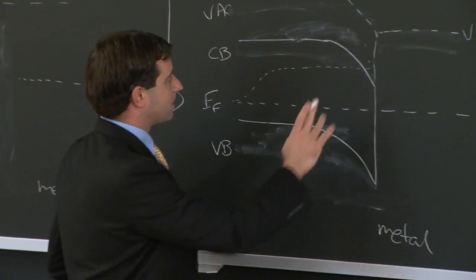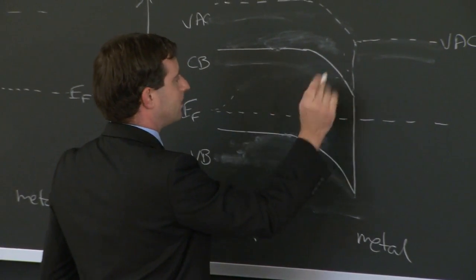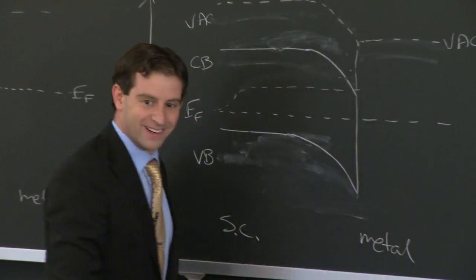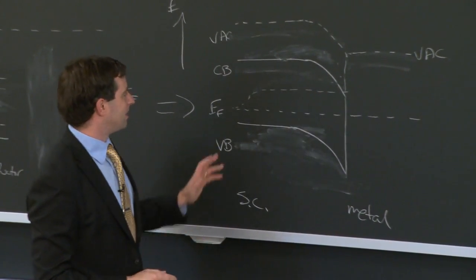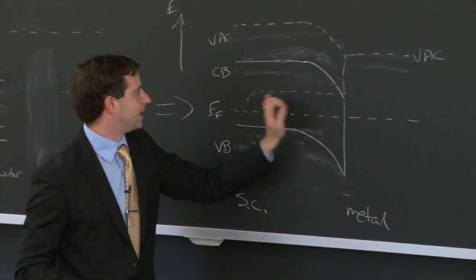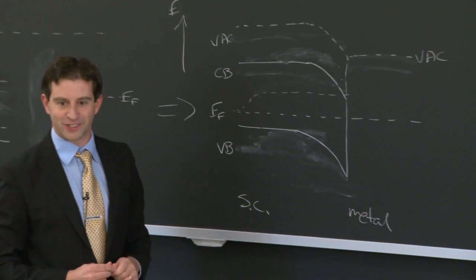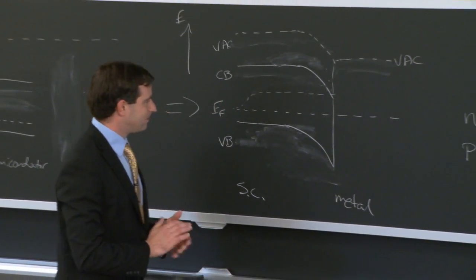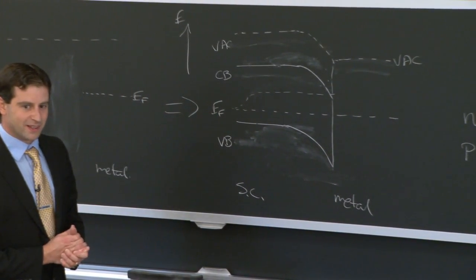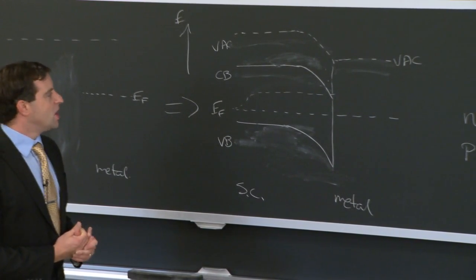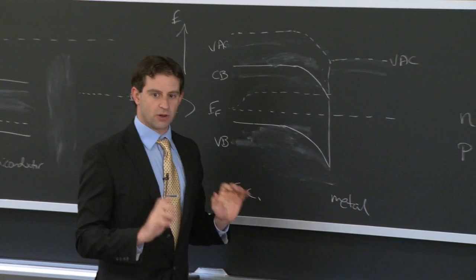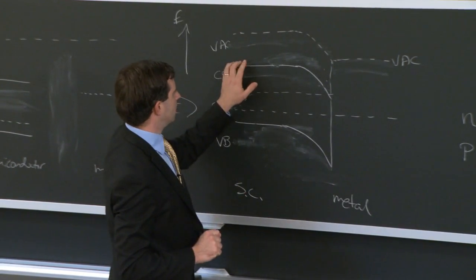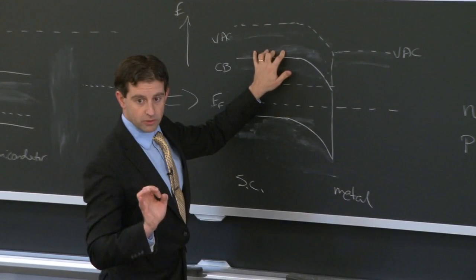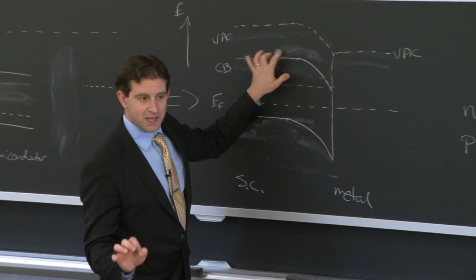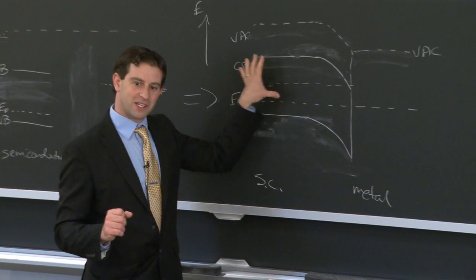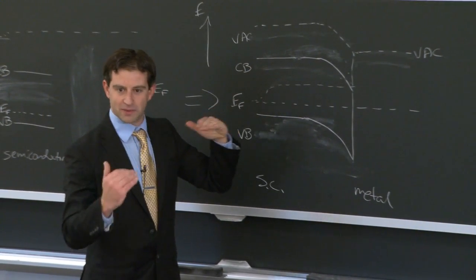Let's make it a little bit, I don't want to get into what's called a two-dimensional electron gas. I'll draw it somewhere down here. So now this distance here is defined by the minority carrier diffusion length, typically from the junction. And then as the electrons drop from that quasi-Fermi energy to the Fermi energy of the metal, what happens? The important thing to think about is that current flow can be reduced to electrons within the conduction band, discrete particles that are seeking to minimize their free energy. The voltage, or the potential across, is dictated by the ensemble. And that's where the Fermi energies come into play.